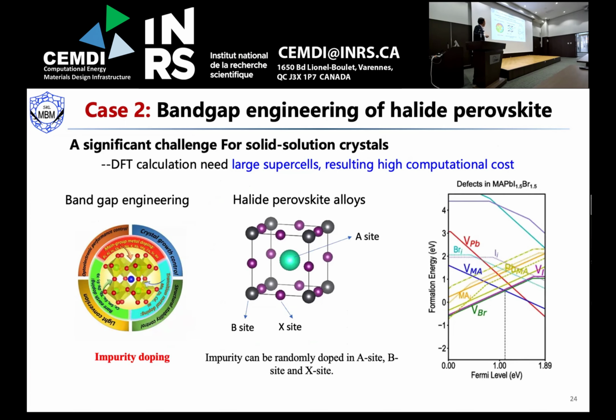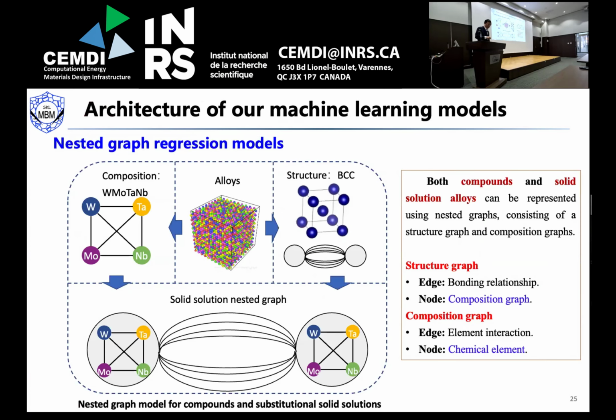Okay. So the second case. The previous talk is mainly about intermetallic alloys. But for solid solution crystals, we have some problems. For example, for the halide perovskite, both the A site, B site, and X site can be doped, and the doping will change the formation energy and the Fermi level. So in this case, we develop our method to a nested graph regression model.